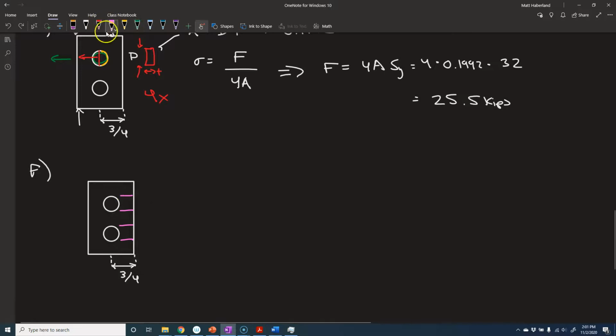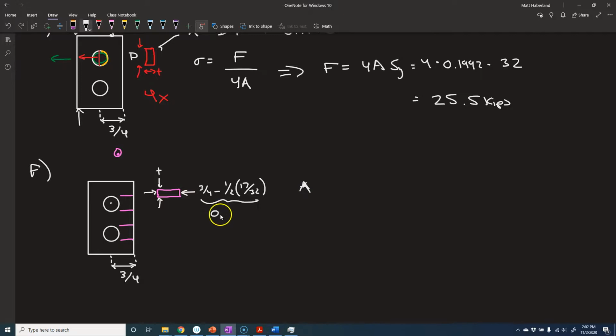And if you look at these from the top down, you're going to see 4 of these all in line. This here is the thickness, and this dimension here is the width of the part, or the distance of the center of the hole, 3/4 inches, minus half the diameter of the hole, 1/2 of 17/32. This distance here is the distance from the center of the hole to the edge of the part minus the hole's radius, half the diameter. This here is almost half an inch.